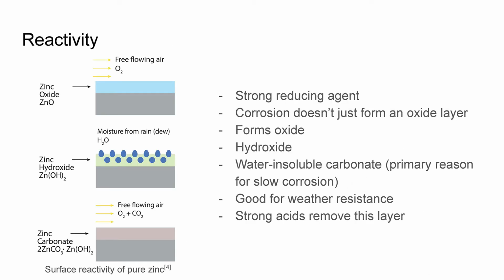So one of the important properties about pure zinc is interesting reactivity. And Parker's going to talk about this a little bit later too, but most of its uses have to do with corrosion resistance. It's a really strong reducing agent, so it really wants to oxidize. But actually, when you have it in an outdoor environment, it doesn't just form an oxide layer. It forms a thin oxide layer, but it also forms a hydroxide layer in moisture, and in a CO2 atmosphere, it forms a carbonate, which is water insoluble, and all of those in combination make it really good at resisting corrosion in weather, which is why they use it as a coating in tin roofs and light poles and handrails and everything outside.